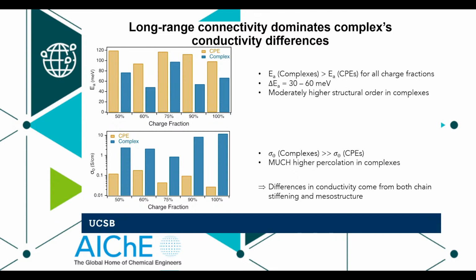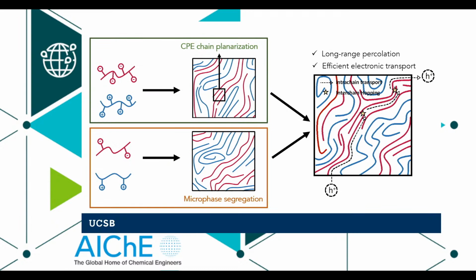That's telling you that you're getting much higher percolation in the complexes, also that the chains are now being kind of forced together via that phase separation to make it easier to transmit charge from one chain to the other chain, okay? And hopefully you'll forgive the fact that we had to do a slightly different system here so you're not seeing all the cartoons.